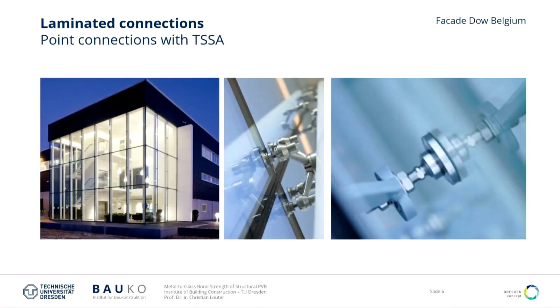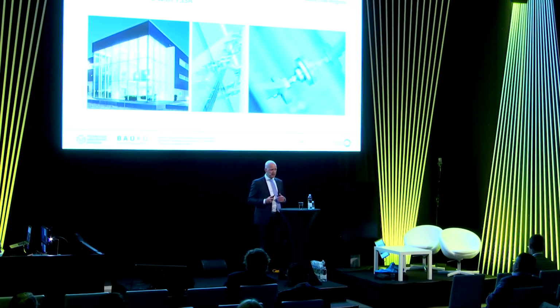Apart from this insert connections, you can, as I said, also make point connections. This is again an example with Sentry glass for a staircase at the Glass Tech. So all these metal connectors are laminated to the glass using the autoclave process, again with Sentry glass in this case. There is also another product on the market, TSSA from Dow. It's a transparent silicon adhesive, by which you can make also point connections that you also laminate to the outside of the glass. You can see some examples here that you glue, adhesively bond, using this film adhesive.